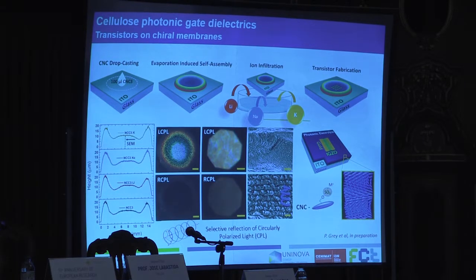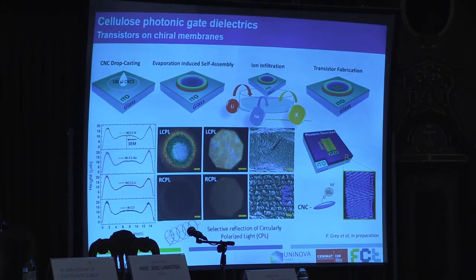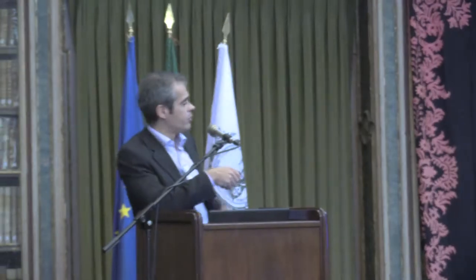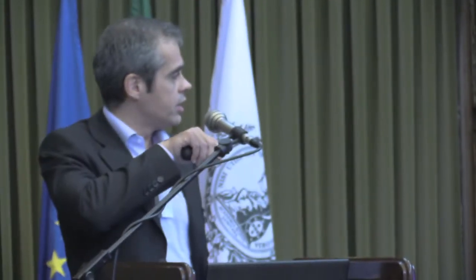And when you let them self-assemble, they will self-assemble with a chiral structure. So there is a rotation of the crystal orientation along the different planes, and you end up with something like this. These chiral structures are very interesting because they can reflect polarized light, depending on whether it is left-handed or right-handed circular polarized light.